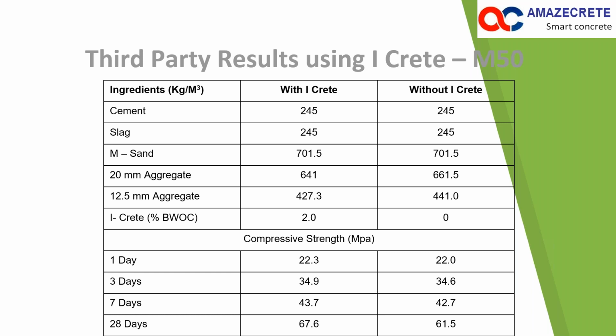But the most important point we need to understand is that when we are using iCrete in such situations where you have to increase the strength, it can take care of some small problems associated with cement or other cementitious materials, and hence it can also act as an insurance in high grade concretes. So at the same level of cementitious content, it enhances the strength. But of course, in this case, you will not be getting any economy. Here the objective is to enhance the strength and other properties. Next.